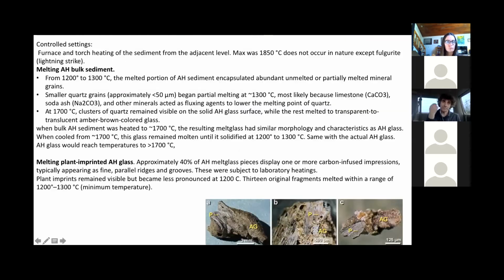A part of this work was done by heating. We basically took various material from the layer and the adjacent sediment and heated it up, because we are dealing with melts. We wanted to know what happened when we melt this material, and what kind of phases appear in a melt and which disappear.